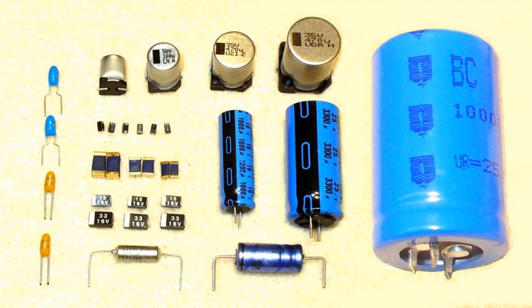Aluminum electrolytic capacitors are very reliable components. Published figures show for low voltage types, 6.3 to 160 volts, FIT rates in the range of 1 to 20 FIT, and for high voltage types, greater than 160 to 550 volts, FIT rates in the range of 20 to 200 FIT. Field failure rates for aluminum ECAPs are in the range of 0.5 to 20 FIT. The published figures show that both capacitor types, tantalum and aluminum, are reliable components, comparable with other electronic components and achieving safe operation for decades under normal conditions.